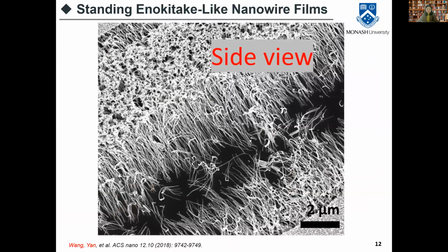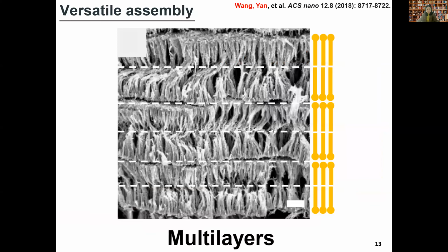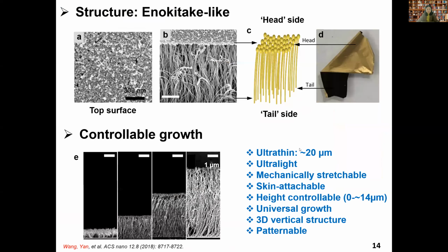The first work is vertically aligned gold nanowires. This gold nanowire film can be put in different configurations. This is an example of the multi-layer structure. The unique feature of this film is that on the top, there are densely packed nanoparticles, and underlying the nanoparticles, there are vertically aligned gold nanowires. The nanoparticle size is around 12 nanometers, and the diameter of the nanowire is around 10 nanometers. And this is the optical image of this gold nanowire film.